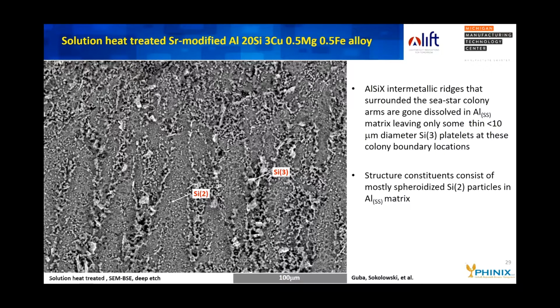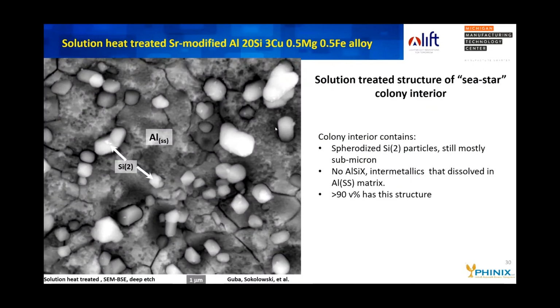So in a deep-etched scanning electron picture, you can now see that where you used to have the colony boundaries, you can still find some silicon-3 platelets, but they're typically less than 10 microns. And the Si2 in the colony arms are still submicron. And here is a higher magnification picture of those submicron spheroidized silicon particles in the colony arm.